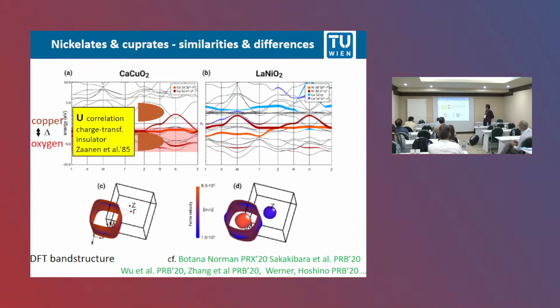Now, how about the nickelates? They also have this x²−y² orbital. It has a very similar hole-like Fermi surface. Now, nickel is to the left in the periodic table, and because of that, this x²−y² orbital is pushed higher in energy with 1 electron, and because of that, it's further away from the oxygen. And because of that, nickelates are not charge transfer insulators, so the holes should go also into this nickel x²−y² orbital.